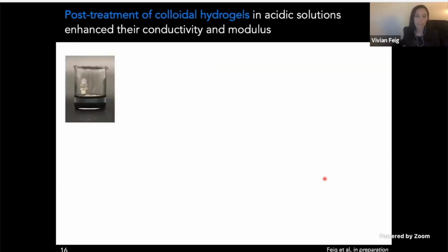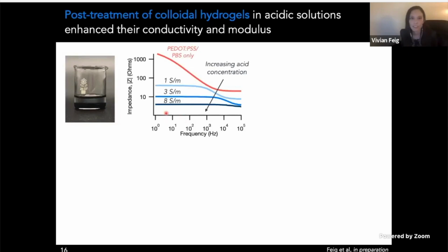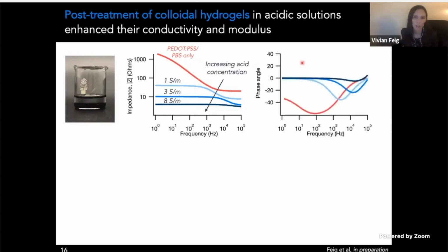So based on this, we were also interested to see if post-treatments could enhance hydrogel conductivities as well. And to test that, we fabricated those low conductivity gels with PBS and immersed them in different concentrations of acetic acid overnight, followed by neutralization in regular phosphate buffered saline to account for differences in pH. And as we expected, the acetic acid treatments also dramatically reduced the impedance of our gels as a function of concentration, as well as changing the phase angle from these low negative values to near zero.